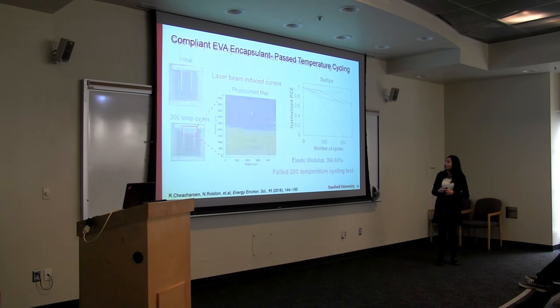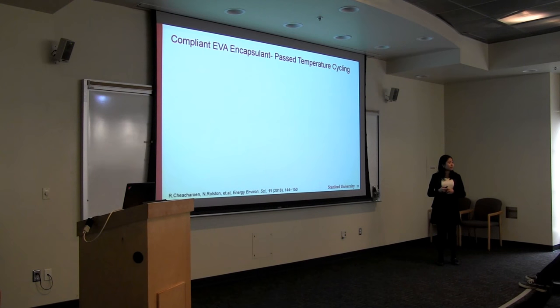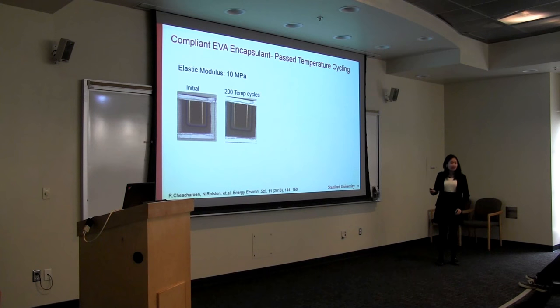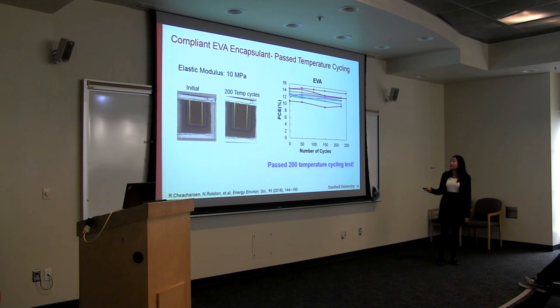So I went ahead and used an EVA, which has only 10 megapascal compared to 400. So it should be more flexible. And I was right. You look at the photo of the solar cell package in EVA, we didn't see any delamination at all after 200 temperature cycles. And all solar cells, in this case all 9 solar cells in 3 different packages, remain pretty much flat. So we passed the temperature cycling test.